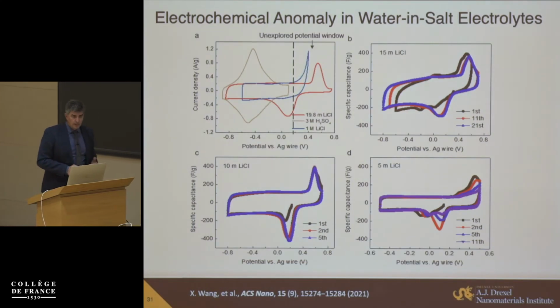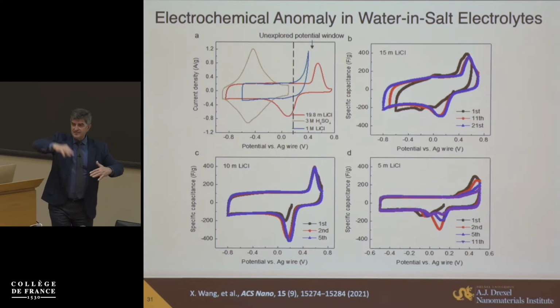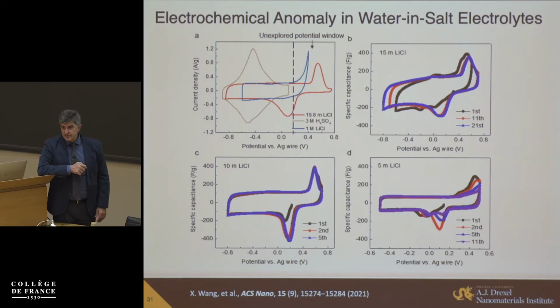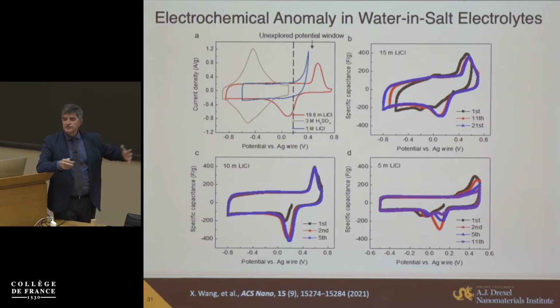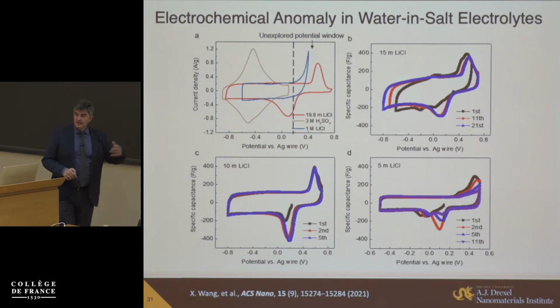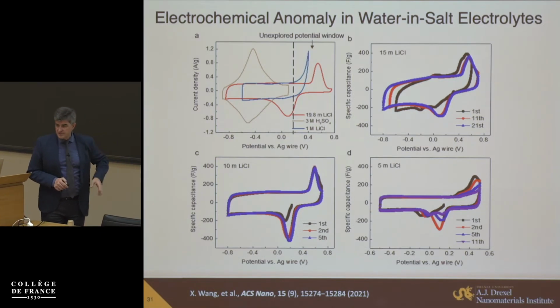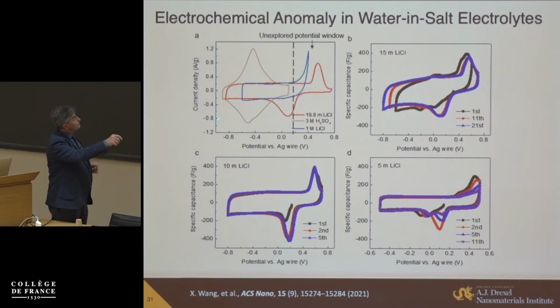Now, recall I mentioned this type of stepwise change in interlayer spacing in MXenes. So we looked at dilute solutions of ions in aqueous electrolyte and protons here. But of course, just like many of you work in water-in-salt electrolytes, trying to expand the voltage window and increase energy density, we followed activities in that field and tried to see what happens when we put MXene in halide electrolytes: chloride, bromide, iodide, and then lithium TFSI as well, at high concentration. And we found very unusual behavior.